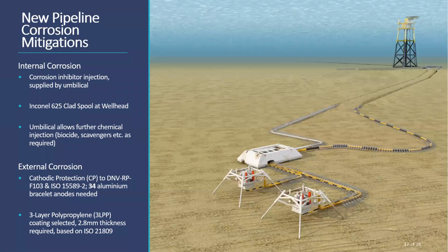Looking at mitigation of the internal corrosion, again, we've proven inhibitors feasible, so we'd choose that for internal corrosion mitigation. We would have that CRA spool at the inlet, and we'd also install an umbilical to allow for further chemical injection as required through life, for things like biocides and scavengers as needed. For external corrosion, we've done cathodic protection calculations to DNV standards and ISO standards. What this told us is we need 34 aluminium bracelet anodes on the whole pipeline to protect against corrosion through life. We've also chosen 3LPP coating because it's got very good coating breakdown factors, and it's widely used in the North Sea. And we've chosen 2.8 mm of thickness based on ISO standards.